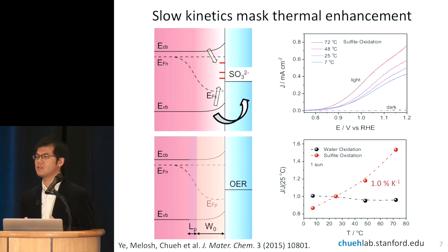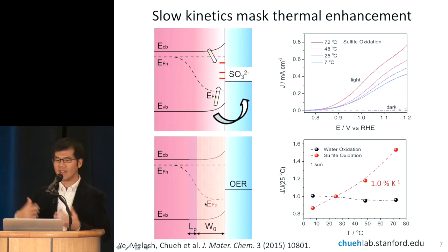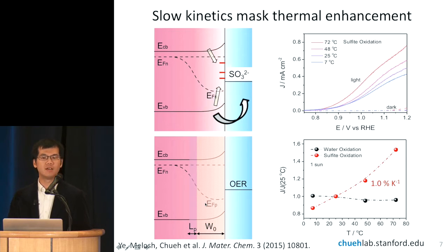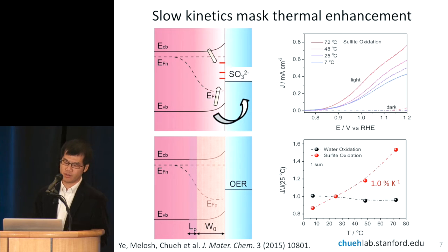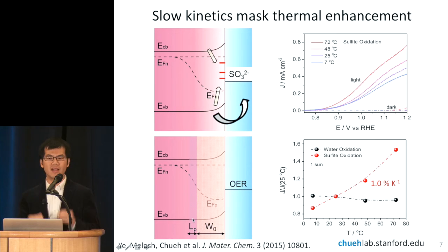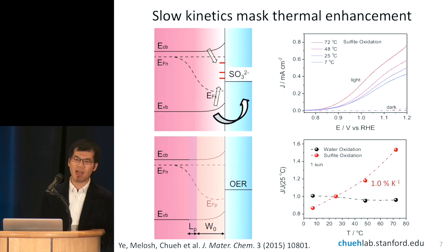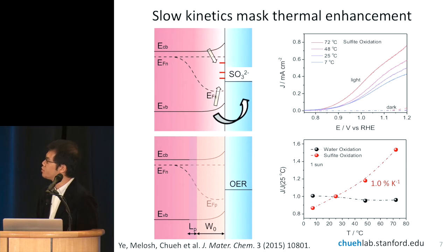One region is assisted by the electric field. This is known as the space charge region, denoted here by W naught. And there's a second region in which the charge separation is facilitated by the diffusion of the carrier. This is driven by a concentration gradient of the charge carrier, and is known as the minority carrier diffusion region. For a material like iron oxide, the two layers are comparable in thickness, a few nanometers for the space charge region and a few nanometers for the minority carrier diffusion length.